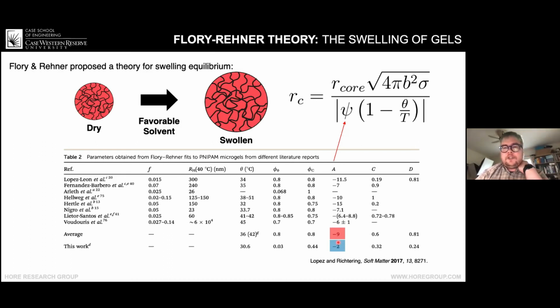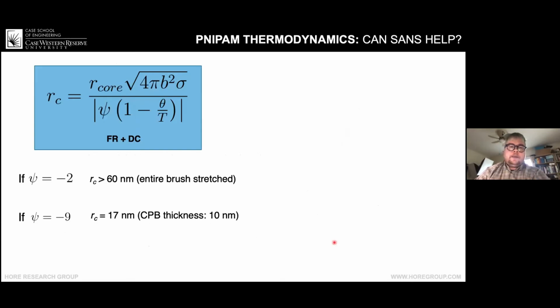So this was our opportunity to test this model. So according to this model, if psi is -2, then the cutoff distance is 60 nanometers between the concentrated and semi-dilute regions, which means the brush will be stretched along the entire contour. But if it's closer to the average value in the literature, then this should be 17 nanometers, which means the thickness of the brush is only about 10 nanometers.